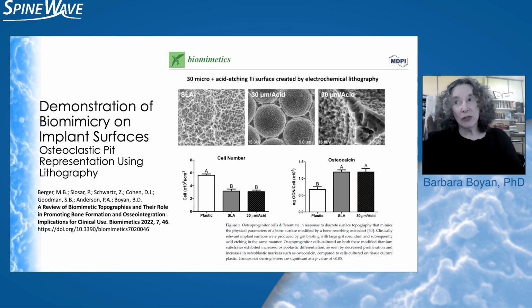To get a better understanding of what features have to be there, this is that SLA surface. You can see these kind of craters, these scallops that are formed by the grit blasting and acid etching. And if you look at the surface up close, you can see that it is not in ridges. It's grit blasted and acid etched. It's little smaller craters and smaller craters. It has a microscale surface and a submicron scale surface. We tried to recreate that surface in a model system.